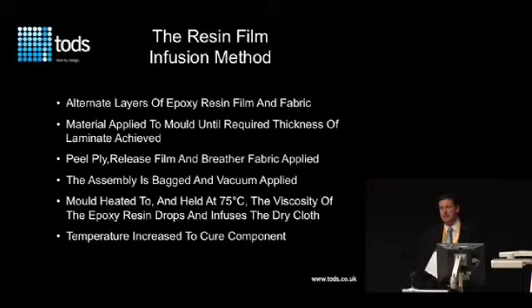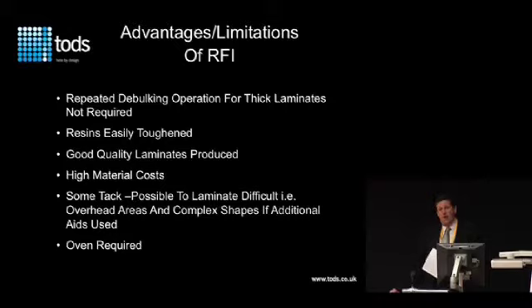Despite Airbus's results, we've found that we can get very good quality, less than 2% air content, but we are talking about a far lower temperature material, which I think is probably more optimized for this product than the materials that Airbus were using. One of the major advantages is you don't have to debulk. You put in as much as you want, then you vacuum bag it and cure it. So you're not tying up a lot of time vacuum debulking.